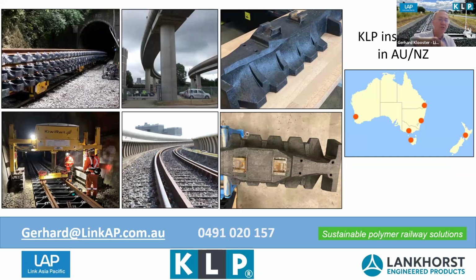We have done push-out forces to determine the shear force. We've done bending tests where you actually see the entire beam bending significantly, 30, 40, 50 millimeters. And then at some stage, you actually hear a snap when the steel breaks. But that is a severe overload case. That would be factor 5 to 10 times the load that it would normally see. So to be honest with you, we don't know. Somebody asked, how will it fail after 50 years? And I guess fatigue is probably the most likely scenario. And even then, you structurally have such stiffness in the polymer itself and the remaining three steel rods in there that you're not going to have any failure, not even on a bridge transom.